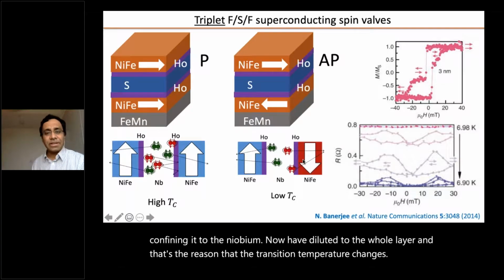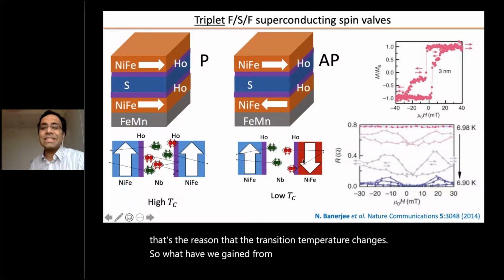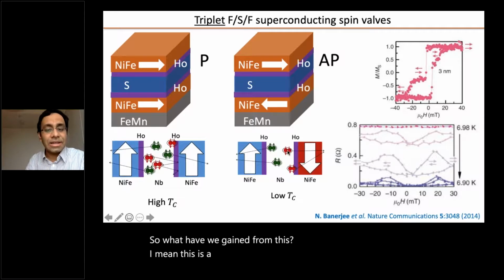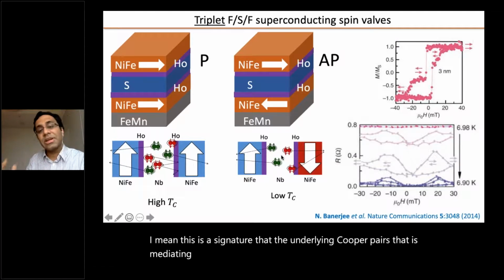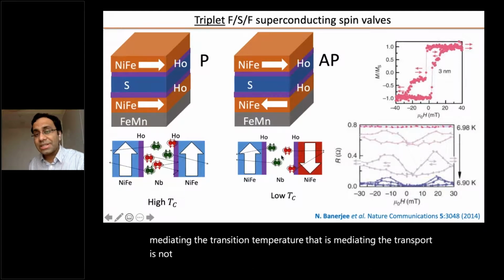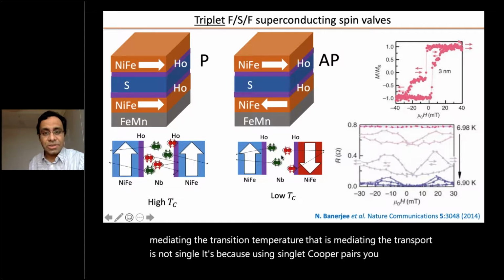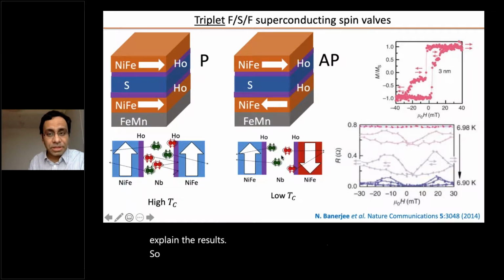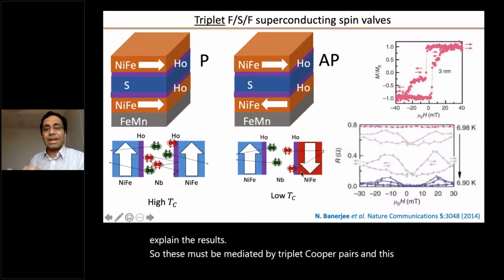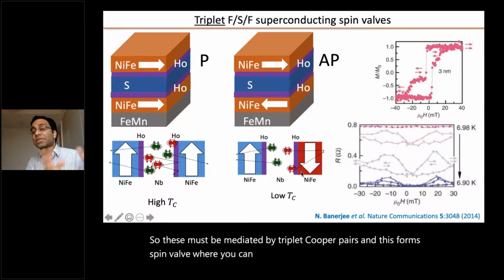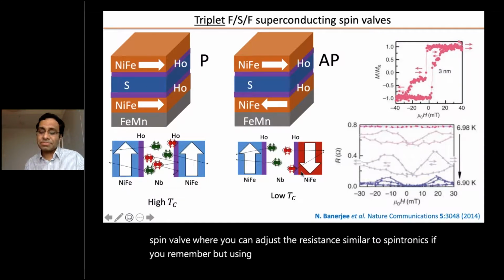So what have we gained from this? This is a signature that the underlying Cooper pairs mediating the transition temperature, mediating the transport, are not singlets, because using singlet Cooper pairs, you cannot explain the results. So these must be mediated by triplet Cooper pairs. And this forms a spin valve where you can adjust the resistance, similar to spintronics if you remember, but now using triplet Cooper pairs.